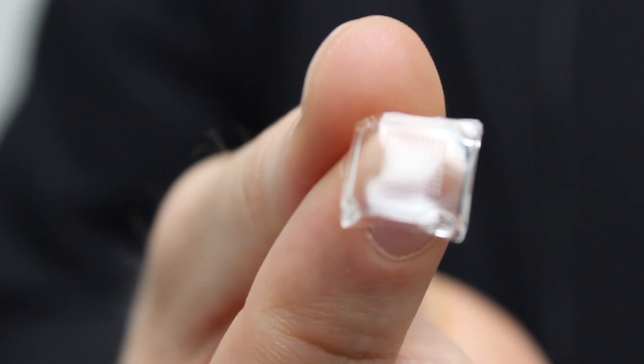This is essentially a similar material to what soft contact lenses are made from. It's hard in the dry state so it can penetrate the skin, but it rapidly then takes in fluid from the viable skin and swells to form a more jelly-like material. It's through this jelly that we can deliver medicines or pick up biomarkers and medicines already in the person's body for monitoring purposes.